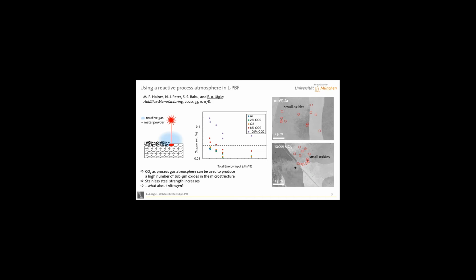As Christian mentioned, of the commercially produced ODS alloys, some of them, like these 9% chromium mechanically alloyed ones, have really tiny oxides, a few nanometers in size. We don't have that here. We have the smallest oxides, and this also holds for the nitrides that we generated in this study that I presented today. The smallest ones are in the order of a dozen nanometers, roughly. So you can still see all of them in SEM. So yeah, this is going roughly in the right direction. Smaller would be better. Volume fractions are also going in the right direction, possibly not there yet.